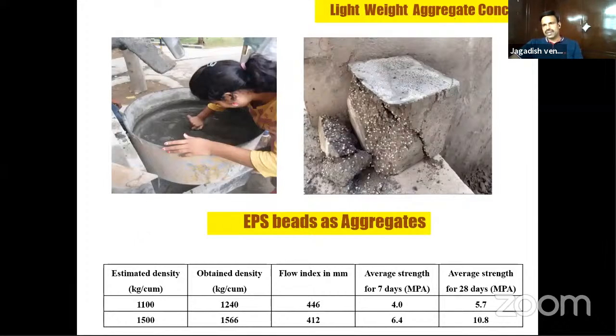This is the work we did for one of the projects in Vijayawada. When they wanted to go for a lightweight slab roof for a clubhouse, we used EPS beads as coarse aggregates, and we were able to reduce the density from 2400 kg per cubic meter to 1200 to 1500 kg per cubic meter with a compressive strength of 10 MPa, because they wanted a little less. This is only for minor applications. So we used EPS beads as aggregates, reduced the density and got the required strength also.